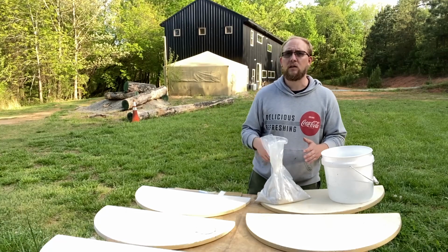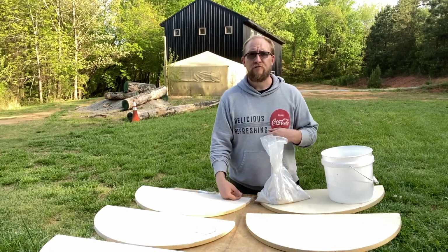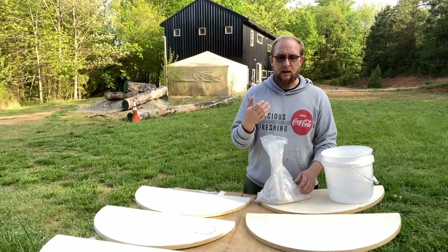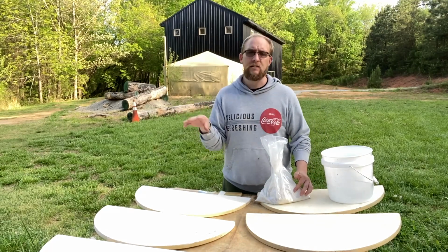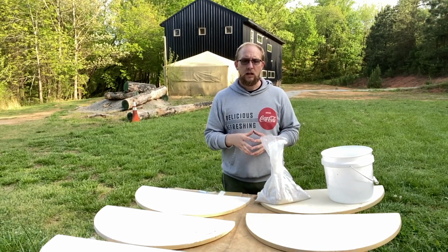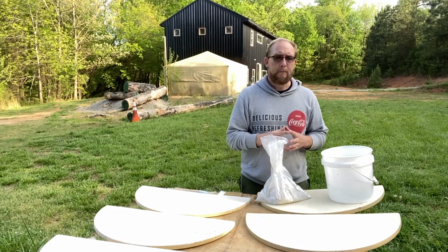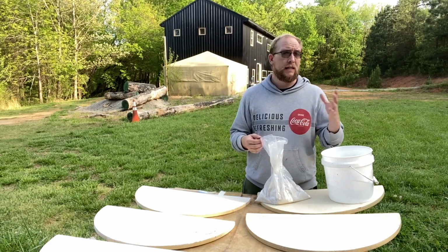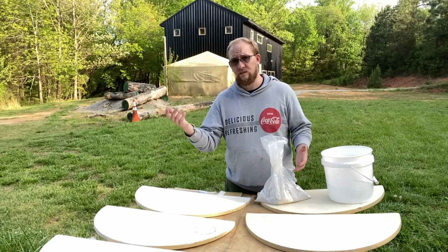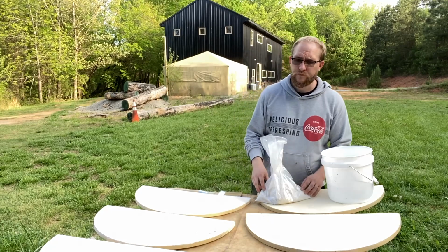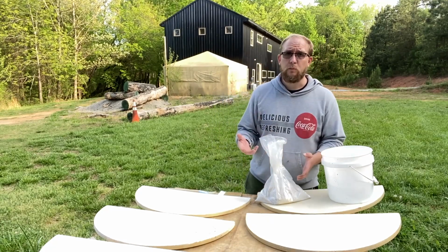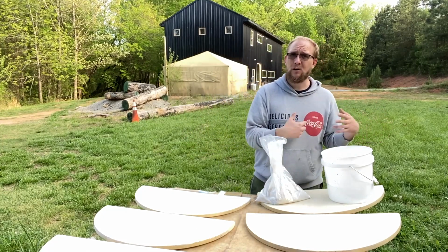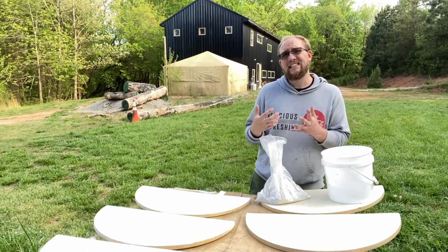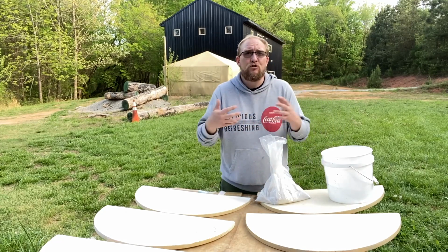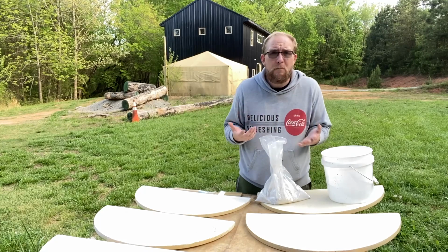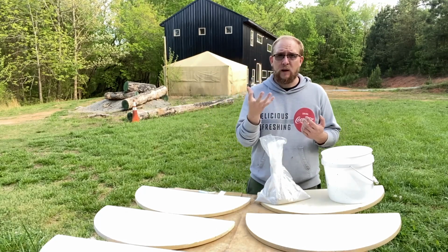Often you'll find a recipe that calls for a 50-50 balance. So you have 50% of one component and 50% of the other. I don't think that's ever true for any situation. I think that's why you're going to have those issues, particularly when it comes to flaking. You have a lot of recipes that say EPK or kaolin 50% and silica the other 50%, or alumina hydrate the other 50%. Now, alumina is going to be the largest component, but when paired with 50% of EPK or kaolin, you're going to have flaking. Why? Because EPK is not a flux of any sort. It doesn't move. It doesn't have really a melting point. So it's going to contract and expand. It's going to have moisture.